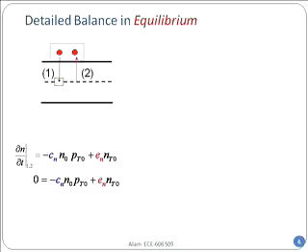Now, do you notice that I have done something which is a little fishy here? I have taken out 1 minus Fc. Do you see? The second term had the 1 minus Fc. I cannot do it in general. I can only do it if the semiconductor is non-degenerate. That Fermi level is way down.